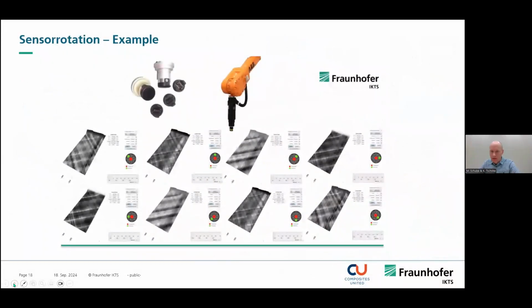So, as you remember, the rotation of the probe takes some time, and therefore we developed a so-called eddy current array, so a small array where the receiving combination rotates over the transmitting coil, and so we can generate different orientations simultaneously. That decreases inspection time a lot.